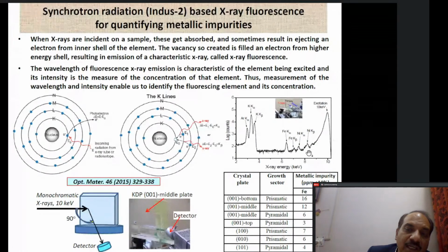Because we know that our KDP crystal, KH2PO4, is having potassium, we know the peak corresponding to K will be there, peaks corresponding to other similar elements will be there, but we were able to find peaks corresponding to Fe and also to some extent aluminium, and these were the impurities which we were looking at, right? So we were able to quantify the metallic impurities present in our KDP crystals using X-ray fluorescence, using the Indus 2 synchrotron radiation source in RRCAT.